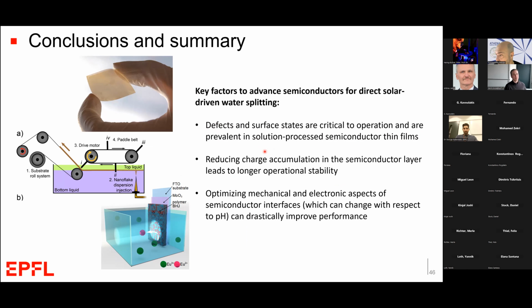And it's especially important with our solution processed semiconductor thin films. We have a lot of defects. We have to deal with these. For the organic semiconductors in particular, limiting or reducing the charge accumulation in the semiconductor layer and preventing any parasitic reactions that can occur will be important for achieving long stability with these systems. And even optimizing the mechanical and electronic aspects of the interfaces, not just for defects, but for increasing stability and for extracting charges is really important for these overall systems.